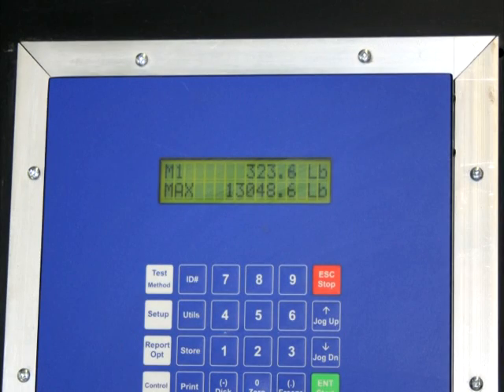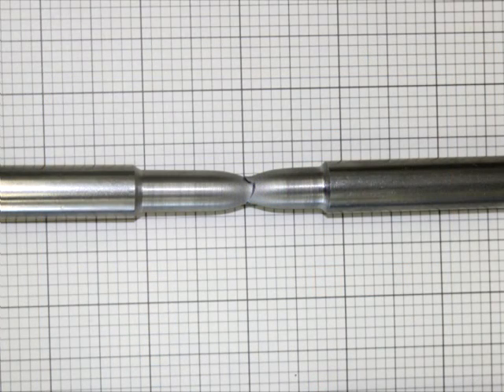And we can see that the maximum force required to break the test part was 13,049 pounds. Multiplied by 8, since my test part was 1/8 of a square inch, that gives me roughly 104,000 pounds per square inch. And that tells me that this isn't, as I mentioned earlier, a piece of mild steel, but it is actually a piece of unhardened 4140 medium carbon alloy steel.